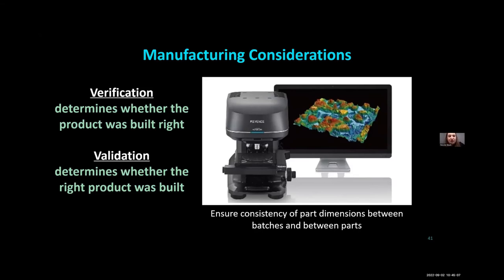And so for verification itself in the manufacturing process, this is really important for 3D printing because as a new manufacturing method, you want to ensure that the prints you're creating are consistent batch to batch. And so this is a big concern to the FDA. So we, in our group, are using this Keyence laser profilometry system to very closely look at what these grafts look like, what the thickness is between batches, and very easily verify that these thicknesses are what we intended them to be.